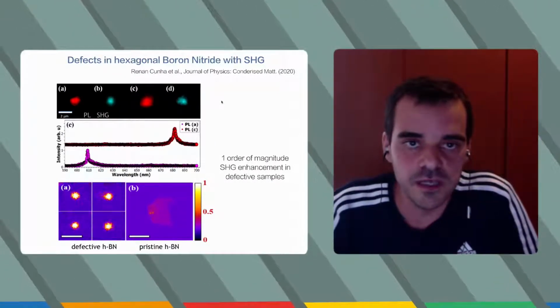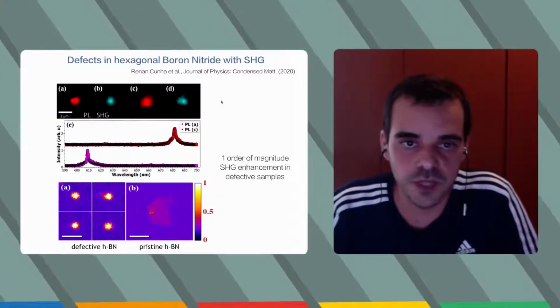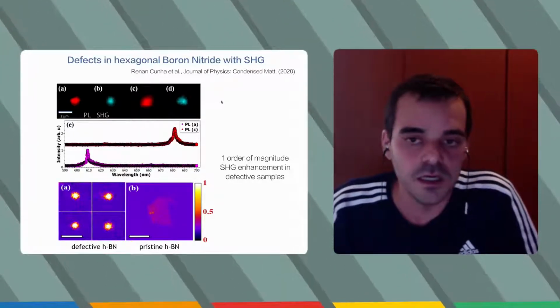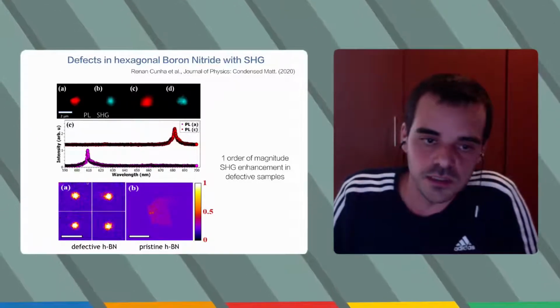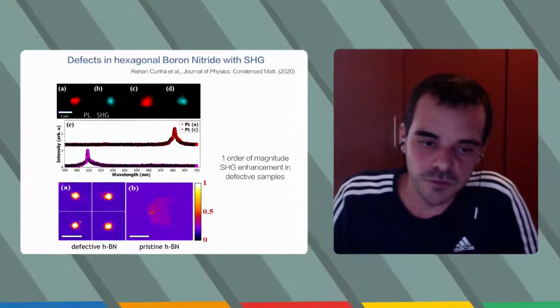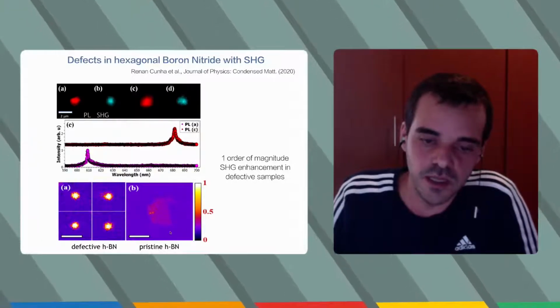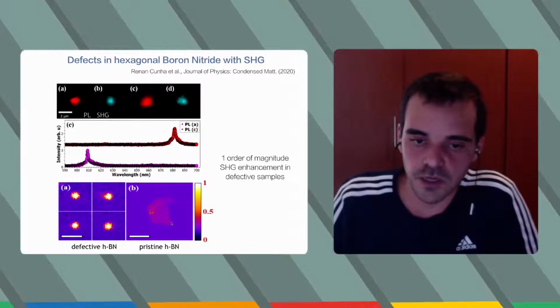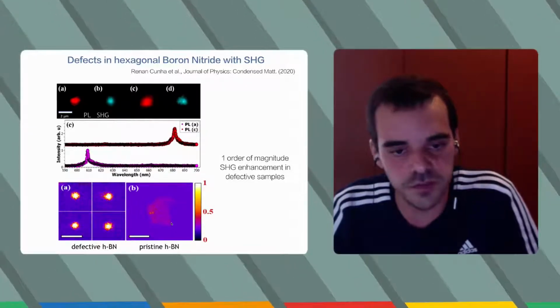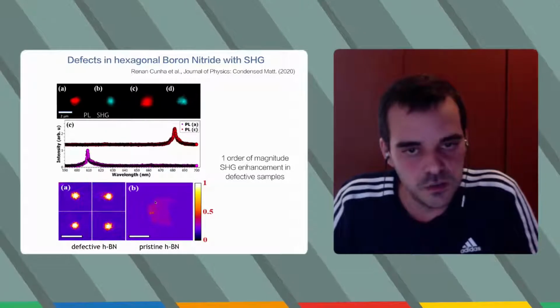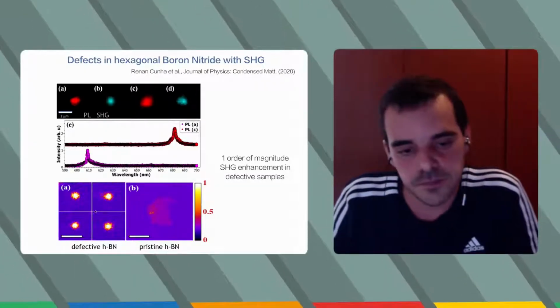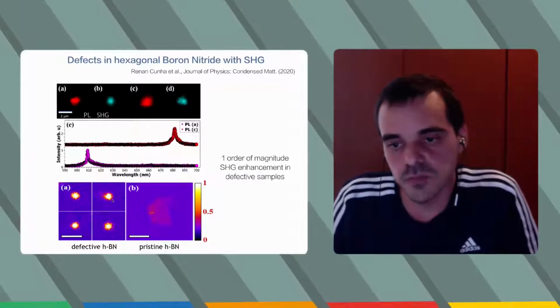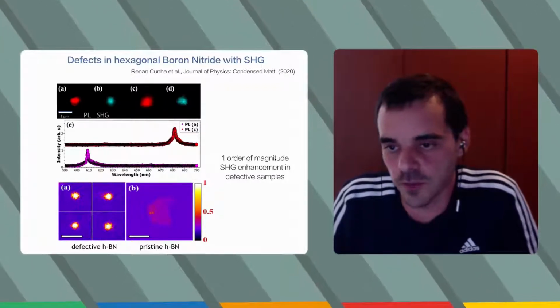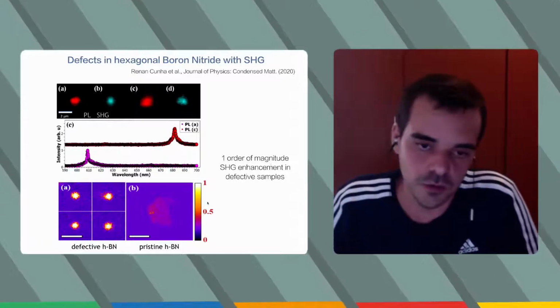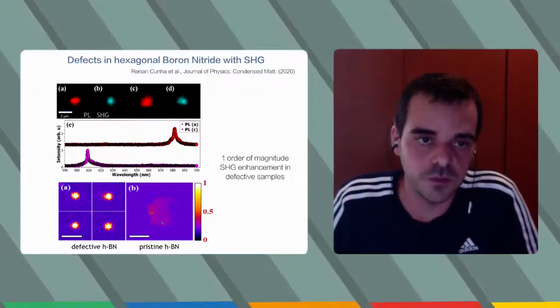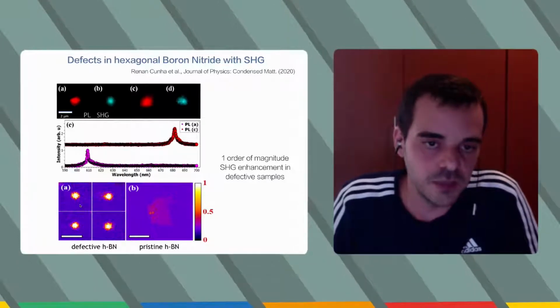We also studied the defects in hexagonal boron nitride by second harmonic generation. We could see that we have a strong second harmonic emission from this defective hexagonal boron nitride, and this is a pristine hexagonal boron nitride with a very low concentration of defects. By comparing these two images, we can see that the defective boron nitride emits much more second harmonic. It's 1 order of magnitude more than the samples with a low defect concentration. We don't know exactly the reason for that.